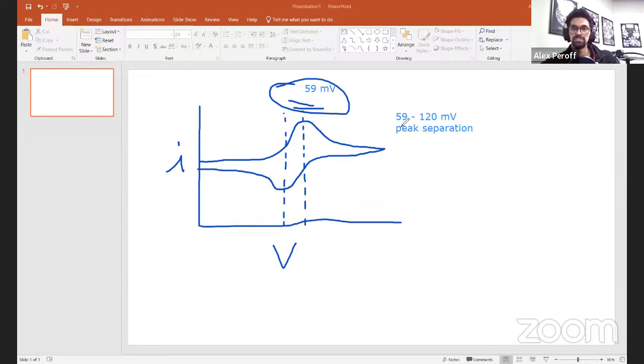Experimentally, you will tend to find that you get numbers closer to 60, 61, 62, 63, 70 millivolts. Some of these are all experimental things. It's not theoretically this value. It's just that in experimental practice, we get peak separations that are different. So that's one of the main reasons: experimentally we just run into this issue.